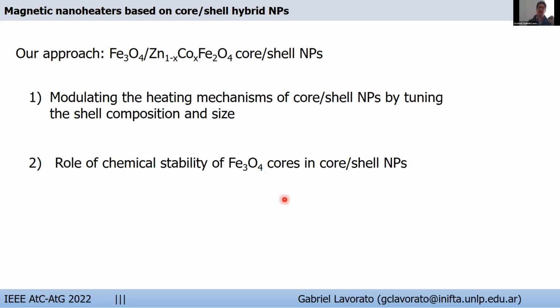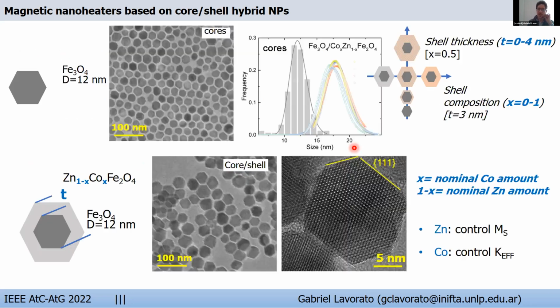And then I will summarize some results regarding the chemical stability of magnetite in this kind of structures. So based on the epitaxial growth of spinel ferrites, our approach consisted in producing magnetite cores with a size of 12 nanometers, which were then covered by a zinc cobalt ferrite in a seed-mediated process. We compare several samples by changing the zinc and the cobalt fraction in the shell for a fixed shell thickness of 3 nanometers, and then by changing the shell thickness for a fixed intermediate composition of zinc and cobalt.